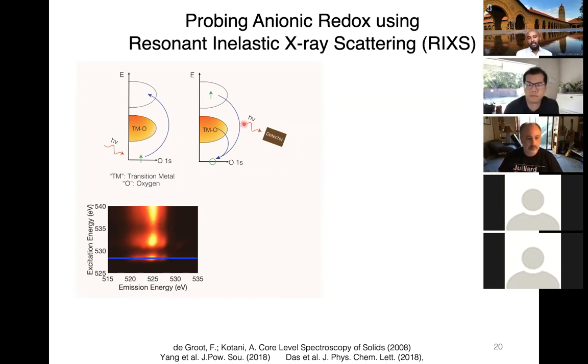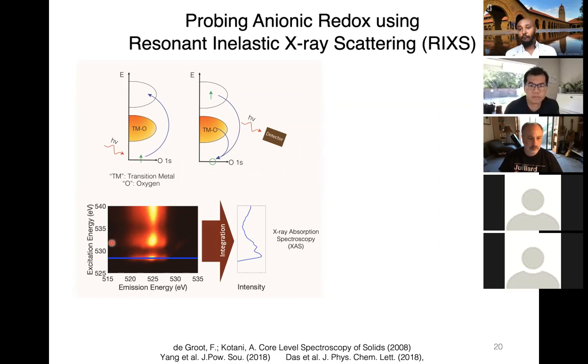If you actually integrate these bright features, or the bright photons, onto the y-axis, you'll be able to obtain information that's similar to what we call X-ray absorption spectroscopy, and this might be more familiar to people who use spectroscopy. They are not the same, but they contain very similar information from different techniques.